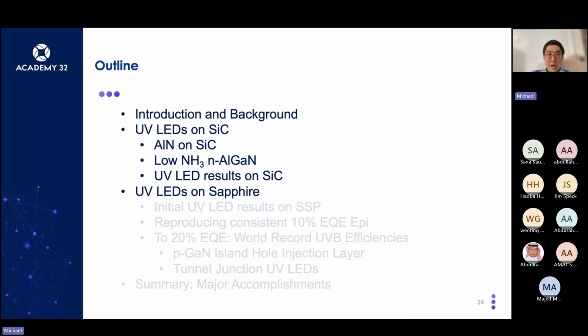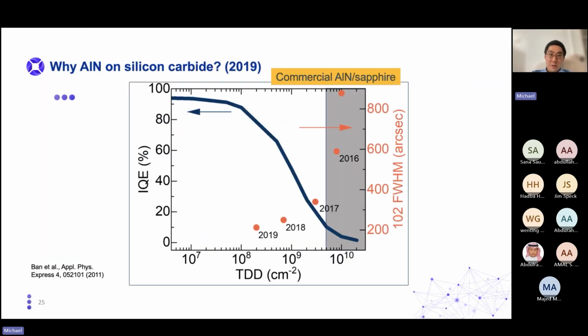UV LEDs on sapphire. I just said that for UV LEDs it was a better choice to grow on silicon carbide than sapphire. So why did we switch back to sapphire? In 2019, it was better to grow UV LEDs on silicon carbide because commercial aluminum nitride on sapphire, and also just homegrown aluminum nitride on sapphire, was extremely defective.